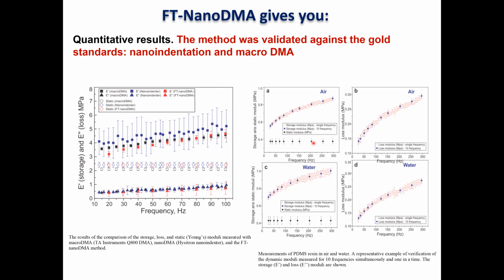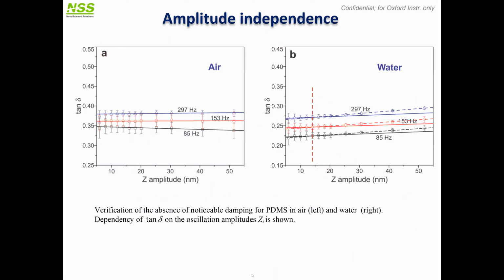So then, of course, you go for, again, the static modulus, and you measure the storage and loss modulus sequentially, and with our 10 frequencies simultaneously. Sequential and simultaneous, and we see the perfect match. Again, this is loss in air. This is for reference, the static modulus. And in water, technically nobody prohibits you from adding whatever liquid you want as soon as it's transparent and using optics to detect the displacement of the cantilever. It works fine.